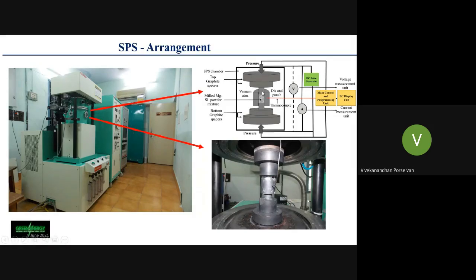So this is how the arrangement is made in SPS. Here we have the graphite die and punches, which are filled with the powder that is needed, and this graphite die and punch is placed between the graphite spacers in the furnace. Thereby, we allow a high density electric current to pass from top to bottom, directly through your material. Thereby, your material physically experiences the high current, which causes Joule heating. Thereby, the sintering occurs. Okay, so this is the simple mechanism of SPS.